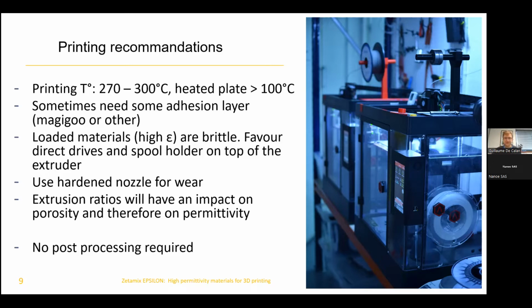So the way we get to high permittivity is by adding a ceramic loading in the filament, a ceramic filler. And these fillers, when you get to high permittivity, so typically the 7.5, make the filament relatively brittle. So we favor direct drives and ideally spool holders that are on top of the extruder, just like you can see on the picture here, to avoid any breakage of the filament. We recommend the use of hardened nozzles because this material is extremely abrasive.